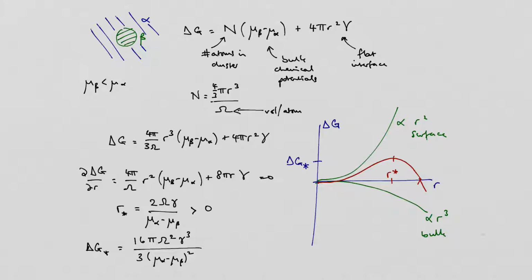Does that make sense? So the difference is whether it's energetically favourable or not to make the infinitesimal separation between the two. Because if it's energetically favourable to make an infinitesimal separation, that's inside the spinodal, then there is no interfacial energy cost for the infinitesimal separation. So the spinodal still occurs and it still proceeds, and it's spontaneous, but you will end up with interface.